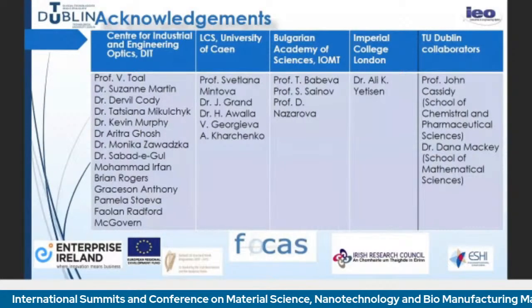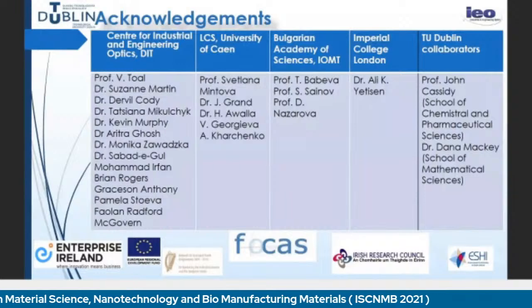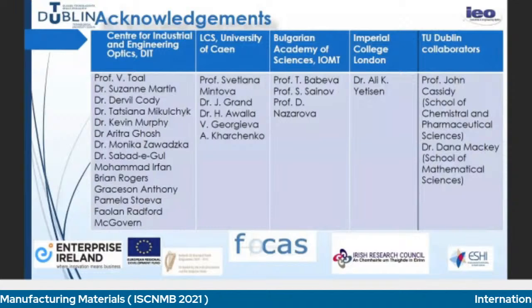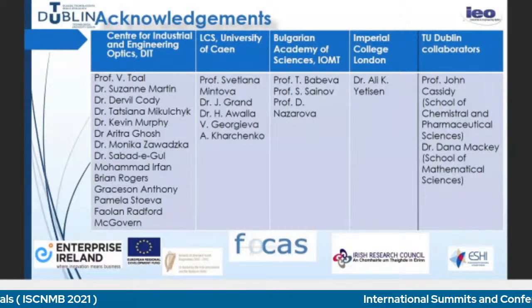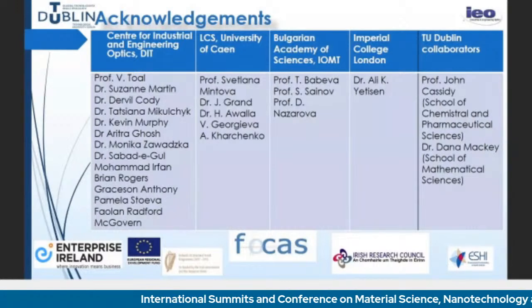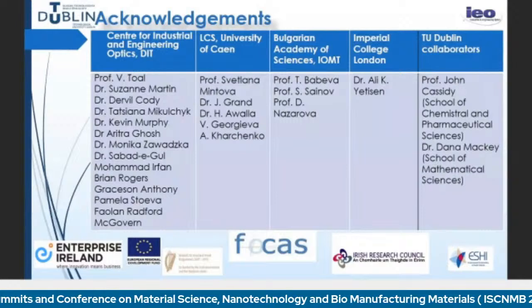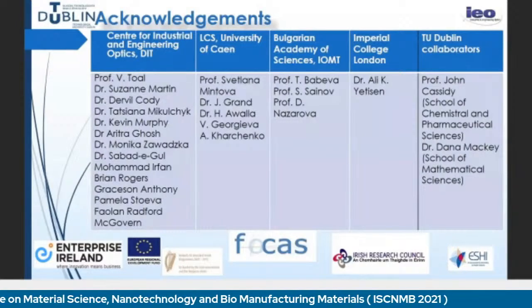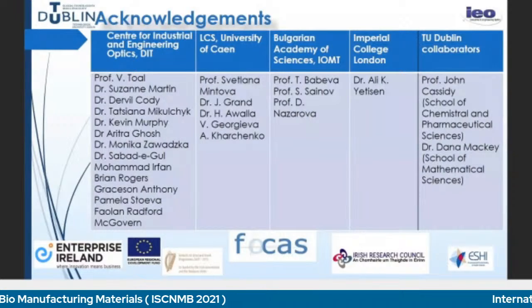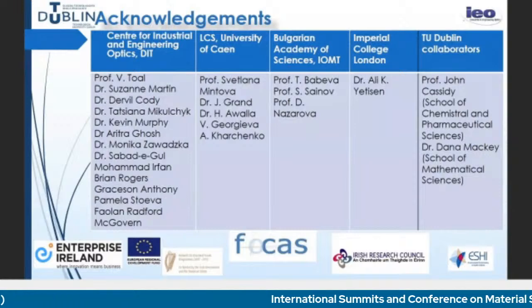And we are working on a sensor that combines a bilayer cantilever with a holographic grating. There we have been able to achieve sensitivity of 0.1%. But as we all know, it's very difficult to achieve very high sensitivity in a very broad range. Yes. If you get a very high sensitivity, it will be a relatively small operational range because otherwise you will saturate your sensor. So it depends very much on the sensitivity.